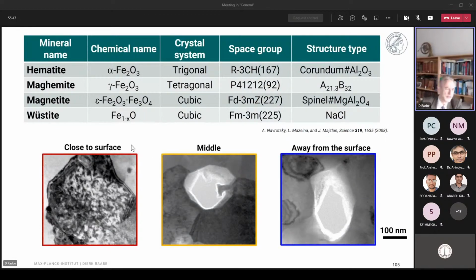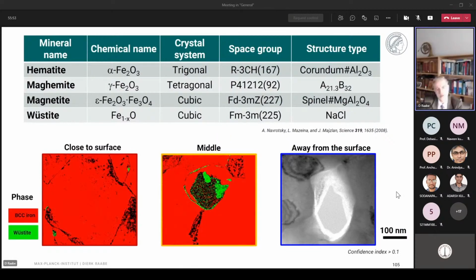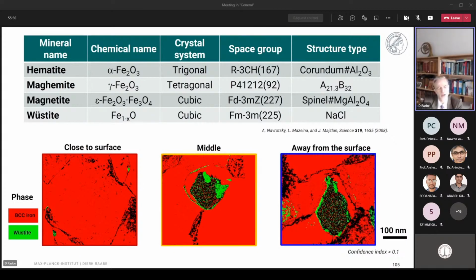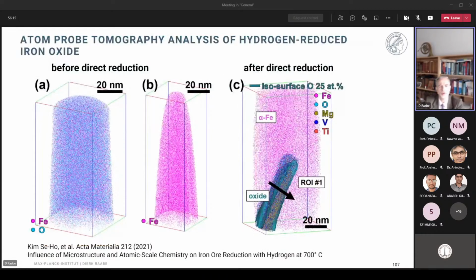So here we studied 3 different types of pores depending on their vicinity to the next nearest surface in this high angular dark field contrast. And we find, interestingly, that the pores that are more remote from the surface have to store the water that is being formed. And that is what you see here. And that leads, with a very high upcoming water pressure, which we again calculate, to a reoxidation of this inner rim of this pore. So that makes the reduction also sluggish.